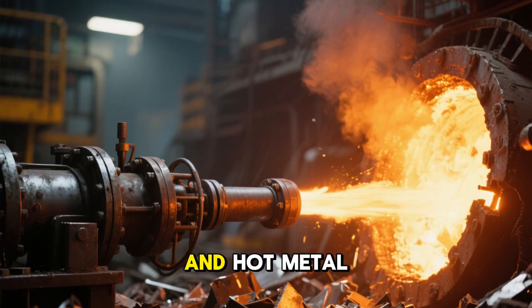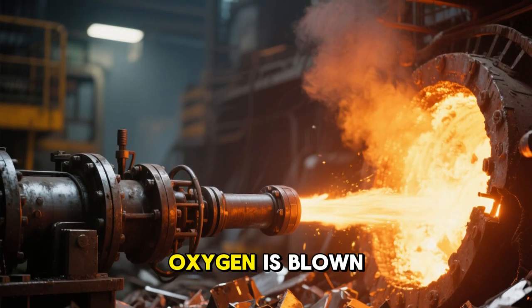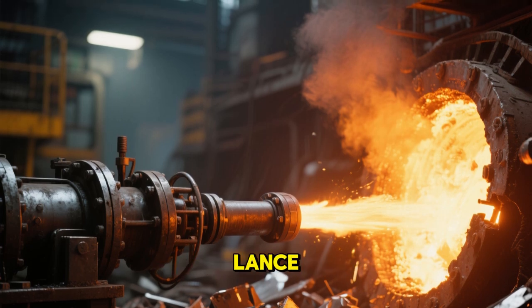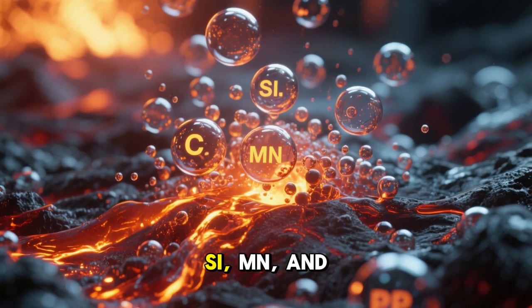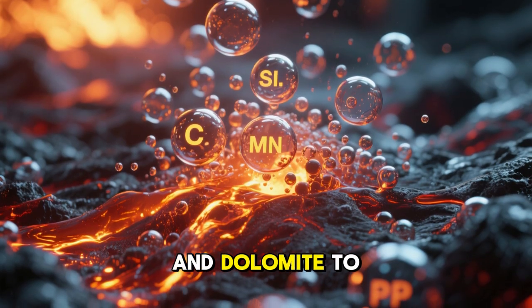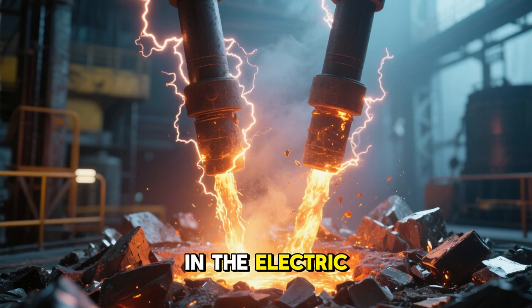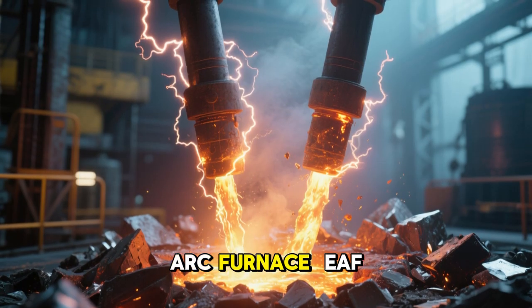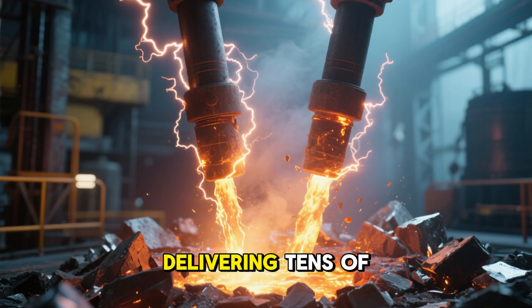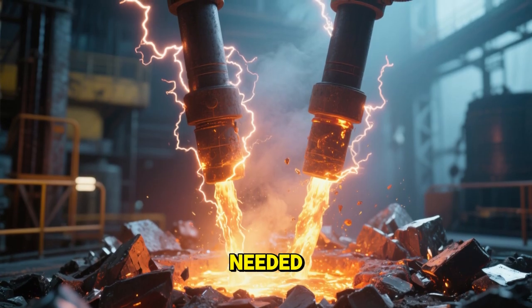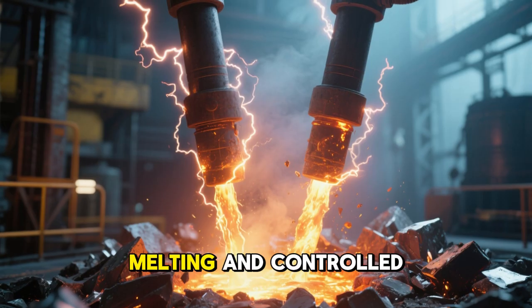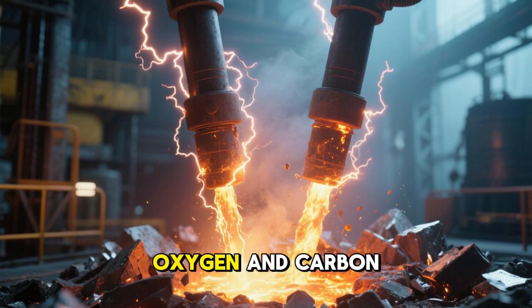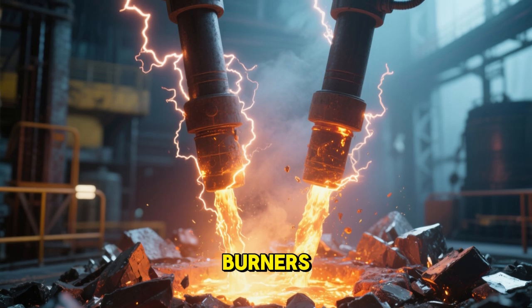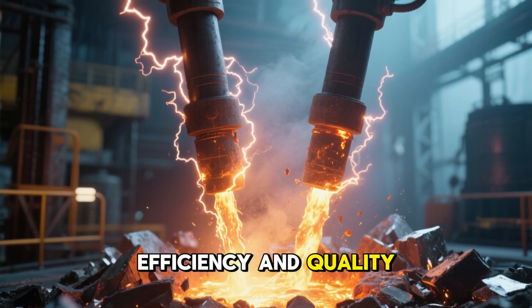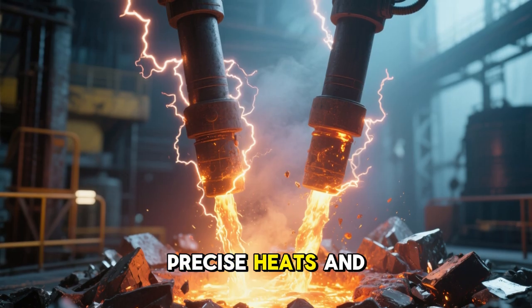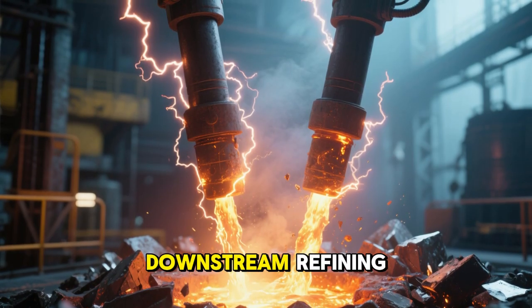Scrap, to absorb heat, and hot metal are charged, then high-purity oxygen is blown from above at sonic velocity through a lance. Oxygen oxidizes C, Si, Mn, and P, with additions of lime and dolomite to capture oxides in the slag. In the electric route, scrap is melted in an electric arc furnace, EAF, by graphite electrodes delivering tens of megawatts. Fluxes and, if needed, DRI-HBI are added. Melting and controlled oxidation remove impurities. Oxygen and carbon injection, foamy slag practice, burners, and injectors improve efficiency and quality. Modern EAFs enable rapid, precise heats and are typically paired with ladle furnaces for downstream refining.